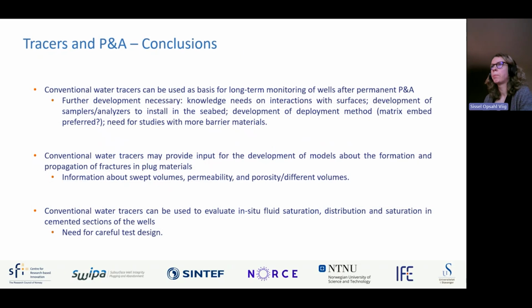So to sum up our results, we see that the conventional water tracers can be used as a basis for long-term monitoring of wells after permanent P&A operation. But there is a need for studying their interaction with different plugging materials, because we have observed that some of the tracers don't behave as expected or as we wanted, together with some selected materials. There is also a need to develop a sampler or analyzer to be installed in the seabed to continuously monitor possible leakages. And there is a need to develop a deployment method of the tracers within the well.